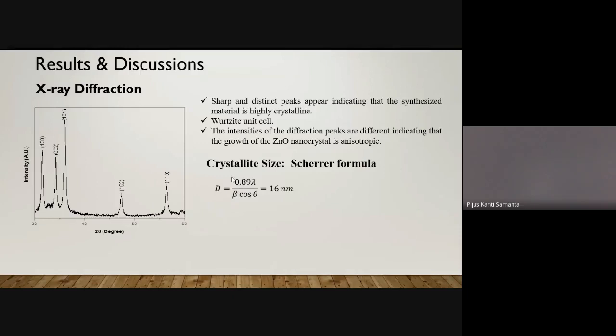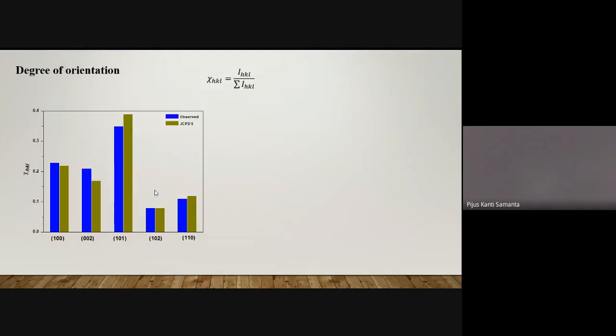And we used a Scherrer formula to calculate the particle size, where beta is the full width at half maxima of the peaks, and theta is the corresponding diffraction angle. And we considered the highest intensity peak for this calculation. This calculation shows that the crystallite size is 16 nanometer, which is very small.